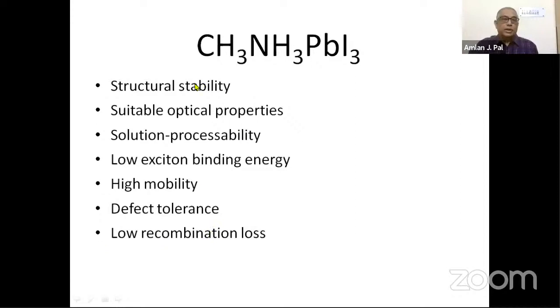Defect tolerance, because since the material is prepared by the solution method, a lot of defects are formed, but still we will show that these defects do not perturb the conduction mechanism. And most importantly, low recombination loss, because the main problem of a solar cell is that you can of course generate excitons, electron-hole pairs, and then dissociate them, but they don't like to stay separated.